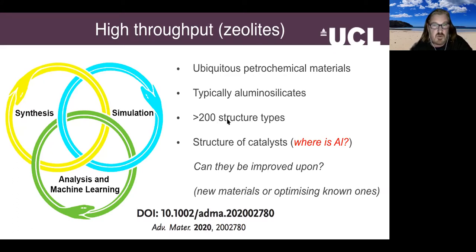Unlike MOFs, where we have 100,000 types of structures, there are just over 200 zeolite structure types, of which a small fraction are actually used in industry. The issue is that for catalysis, we want to identify a structure-activity relationship to understand what makes a good catalyst. That boils down to, amongst other things, identifying where the aluminium is in the structure, and we can't use experiment to identify that unambiguously. And so this is why we're using simulation. The idea is that once we identify the structure, we can say whether it can be improved upon in some way, or we might even identify some new materials.